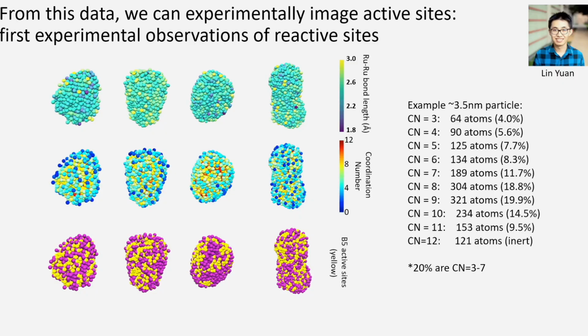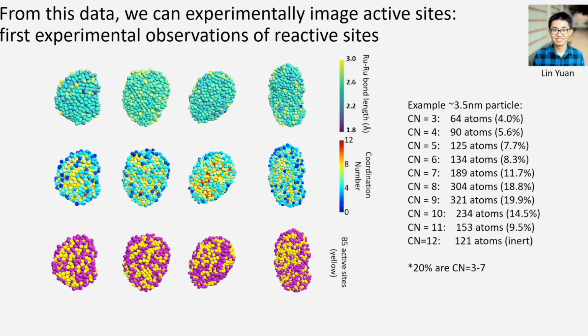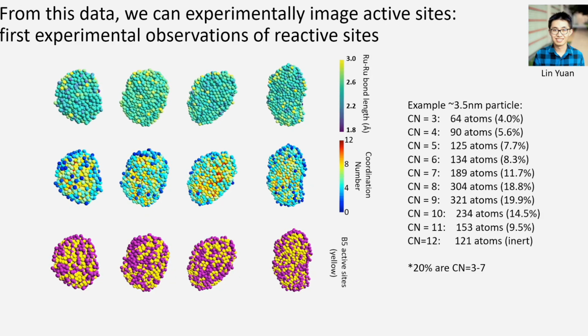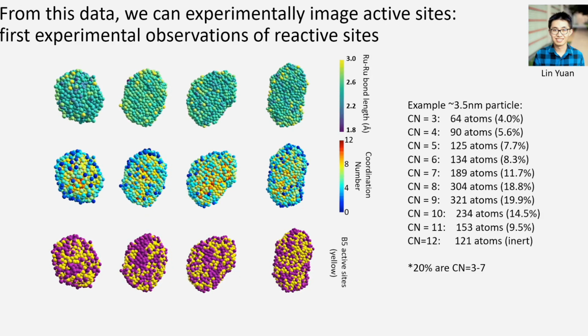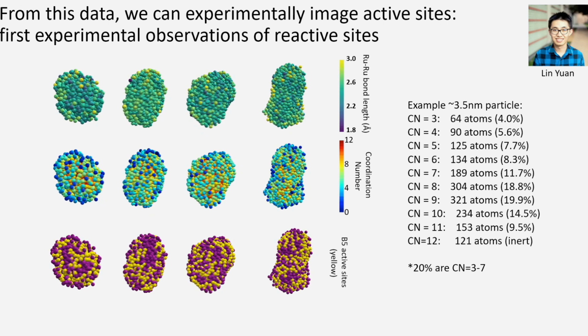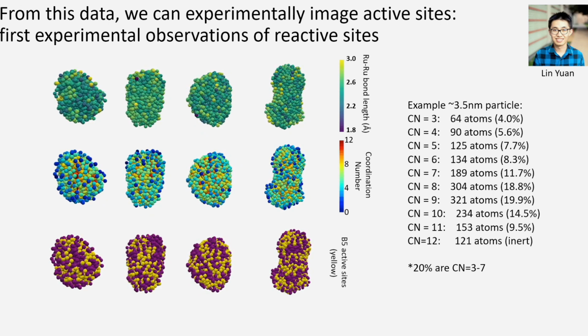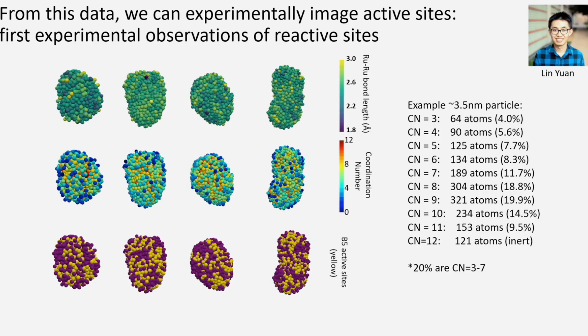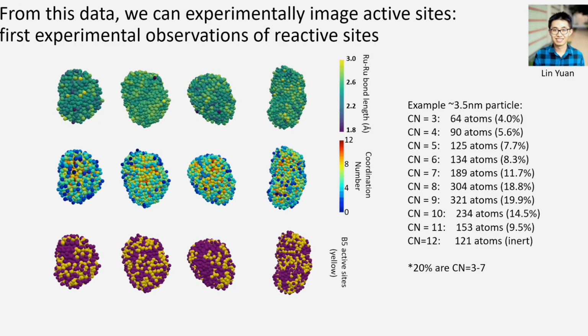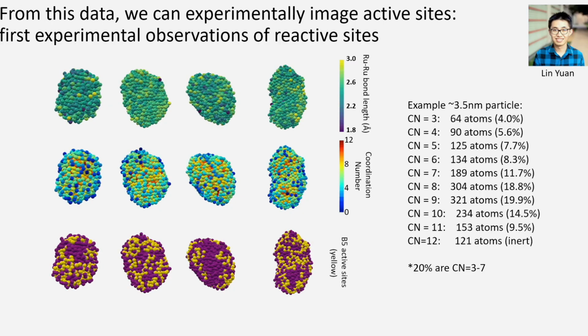And we can do this over different size nanoparticles and different composition nanoparticles. And what we start to see is we can look at the ruthenium-ruthenium bond length, the coordination number, and then from there basically extract what are the B5 active sites. And what we're seeing is that when we have catalysts that are somewhere between basically the 2 and 3.5 nanometer regime, basically about 20% of the catalyst surface corresponds to those B5 active sites. So now what we can go and do is drill down into those active sites and basically see how they're being changed when we have hydrogen and when we have nitrogen in the environment.